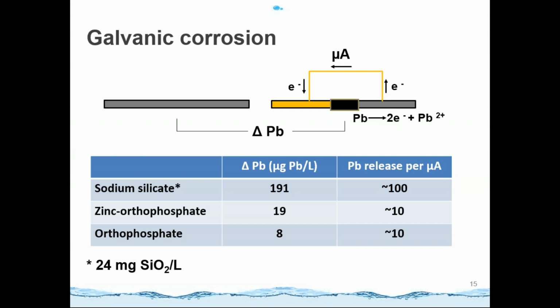We compared the increase of the lead with the galvanic current we measured between the copper side and the lead side. As we can see, in the orthophosphate treated system, 1 microampere only increased lead by 10 micrograms per liter. However, in the sodium silicate treated system, 1 microampere increased lead by around 100 micrograms per liter. So it means the corrosion scale formed in the sodium silicate treated system cannot store the lead released from the galvanic reaction.